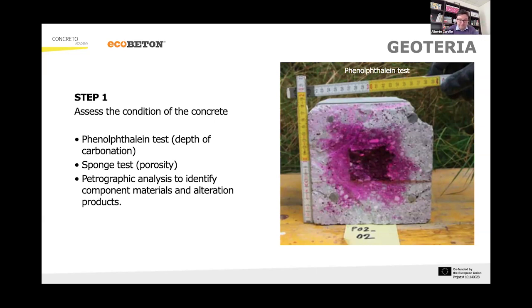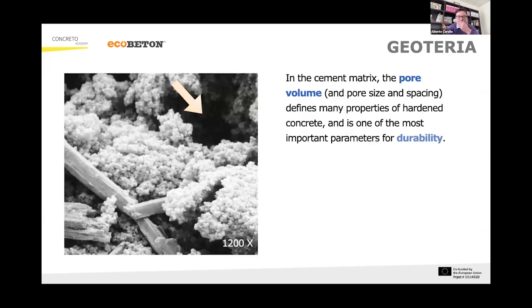Then we do a porosity test and then a petrographic analysis. Why porosity test? It is so important because of the pore volume. Here I put you microscope pictures and you see the voids. These are the pores, because when you make concrete, there is a lot of water inside, and then water eventually evaporates from concrete and leaves a hole, and that is related to durability of everything, because through those holes, all the pollution, carbonation, chlorides, everything is penetrating and destroying concrete. So knowing the porosity is fundamental to do a reparation.